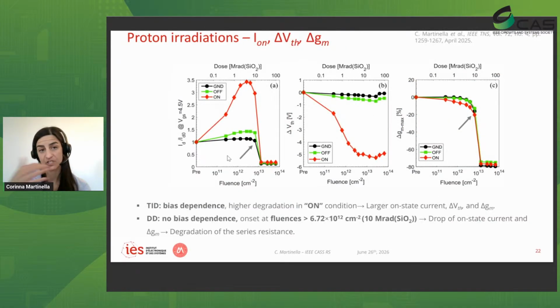Once again, there is a proportionality with respect to the gate bias during irradiation. We can see that total ionizing dose, for example, if you look at the delta of the threshold voltage, it's higher when we are in on state with respect to off state and ground. However, the onset of the displacement damage is clearly the same independently of the bias that is applied on the gate, because that's a material property.